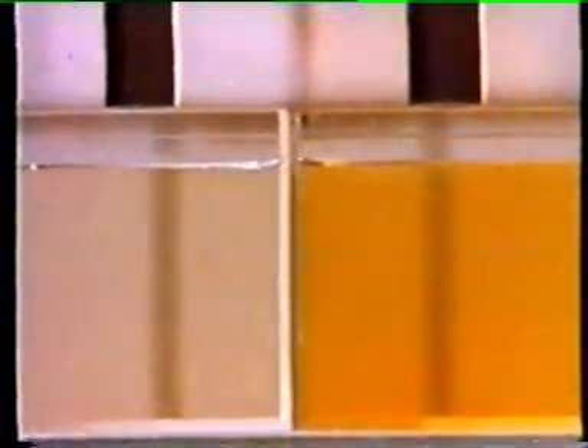Here is a simple demonstration. The jar on the left contains water, that on the right, oil. We shall quench 2 identical test pieces from the same temperature. The sample in the water is enveloped by a blanket of vapor which quickly breaks up, allowing water into contact with the metal. But the sample in the oil bath is still surrounded by the vapor blanket, and cooling is slow, until this breaks up. You see it happening now.